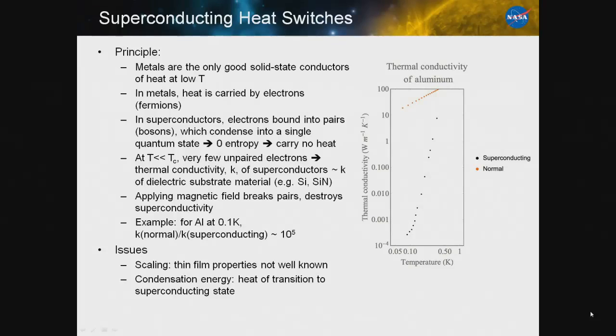Well, to get good conductance, you need a metal, because metals are the only good solid-state conductors at low temperatures. They're good conductors because they carry heat through electrons. But in superconducting metals, below their transition temperature, the electrons get bound into pairs. The pairs condense into a single quantum state and thus have zero entropy and thus carry no heat. So at temperatures far below the critical temperature, the thermal conductivity of metallic superconductors approaches that of dielectric materials like your structure, such as silicon or silicon nitride.